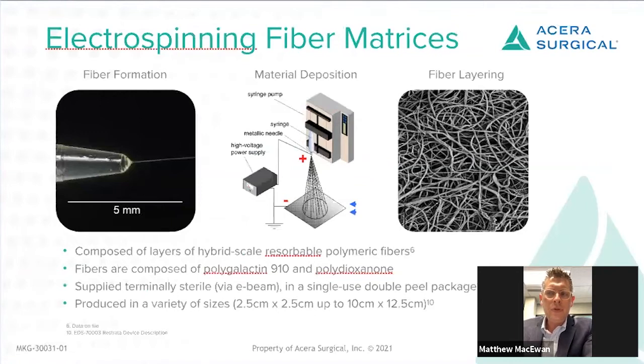And to do that, we turned to this technology called electrospinning, which has been around for a long time. It is uniquely able to make very small diameter fibers. We turned to this technology mainly because we found that it would allow us to create non-woven fibrillar matrices that look very much like, and essentially mimic, native ECM. So what we do is take resorbable and biocompatible polymers, dissolve them with solvents into a liquid, and then shoot them out of these very small nozzles that you can see here on the left-hand side of the screen. What happens is it pulls a very small bead of this polymer out of the nozzle.